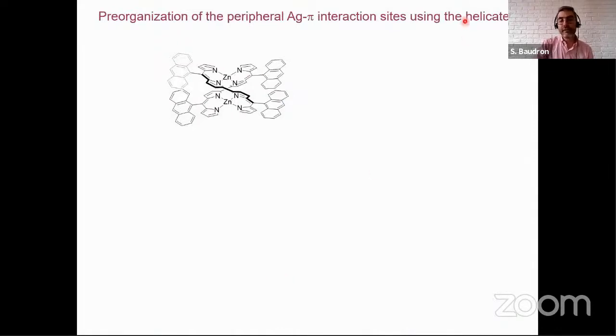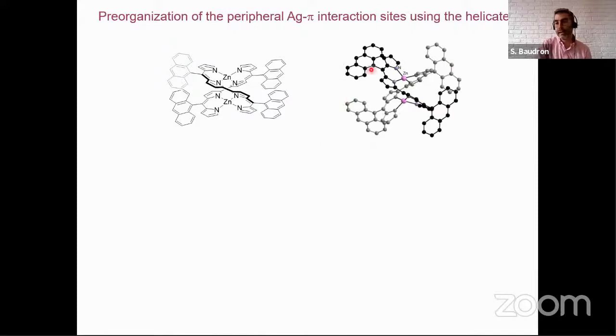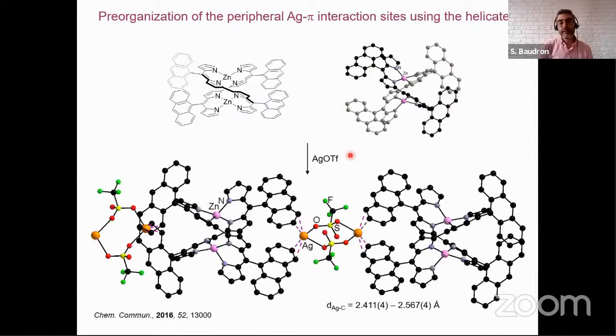Then we went on to investigate the role of a peripheral group at the periphery and to see whether its pre-organization by coordination of a tetrapyrrolic system to the zinc(II) cation could be used for complexation of silver(I) cations. We prepared this new helicate, as you can see in the crystal structure here, and studied its complexation towards a silver(I) cation. In this case we have silver-pi interaction with the anthracene group at the periphery, not with a pyrrolic system. So we have a system that is rather analogous to what had been studied previously with polyaromatic architectures, but in this case it involves a metal complex, in that instance a helicate.